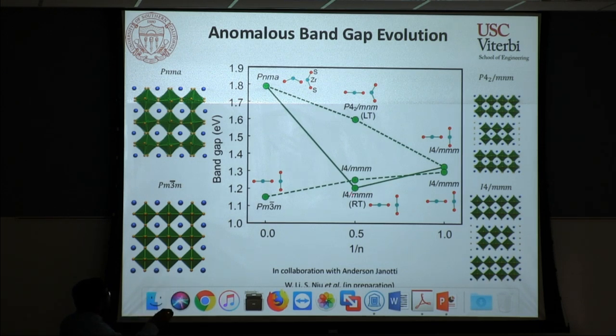Now, in principle, most of the oxide and halide perovskites that we saw earlier did not have a substantial difference in how the octahedral tilting happens in these systems, but the dominant effect in all those cases was just quantum confinement. You just take a perovskite block, put a layer, and hence reduce the dimensionality of your system. So we took this material system and removed all this octahedral rotation that was present in the perovskite, and we got this Pm-3m phase, which is a nice symmetric perovskite.